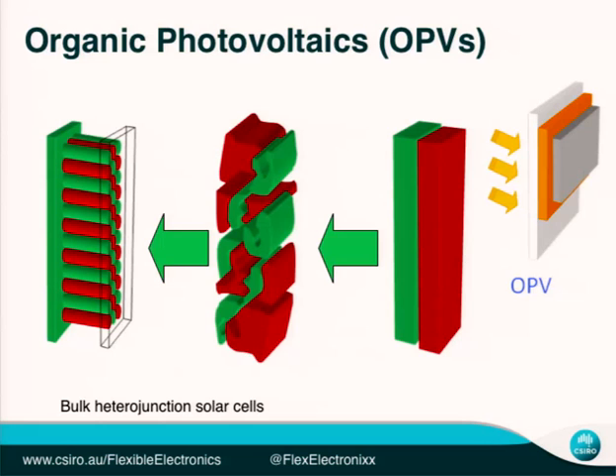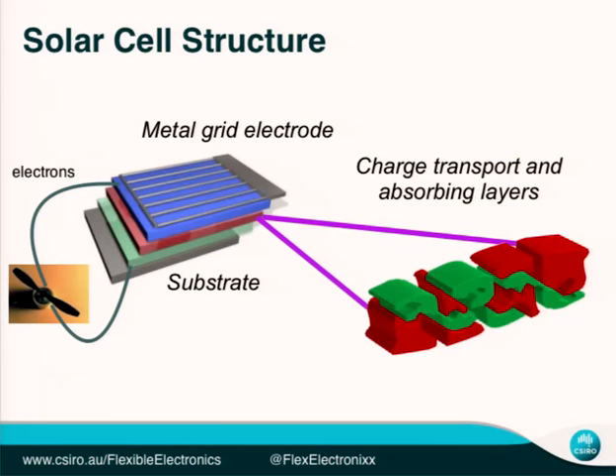So we take this bulk heterojunction here and we put it between two electrodes, and one's transparent, at least one is transparent, and then put another electrode on top of it. But that's really about it. It's not a lot more complicated than that, maybe some little interface layers on the top. But that layer is between about 80 and 300 nanometers thick, so it's really, really thin, very small amounts of material.